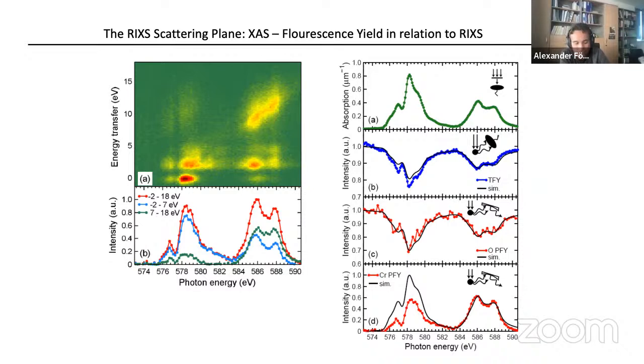And so, typically one embarks on a series of materials which one studies, and I would really say take the time to measure two, 3 cases where you know they are definitely chemically very different, and see how far up you would go until they collapse, and that gives you certainty about the normalization.